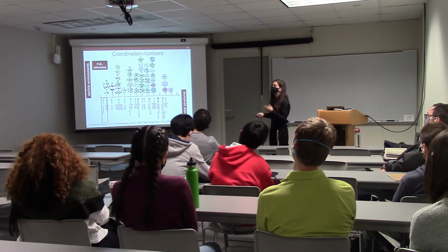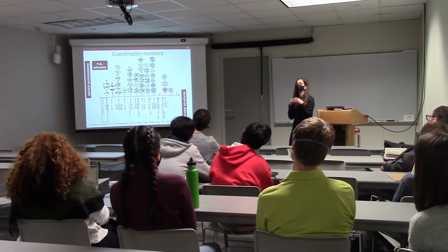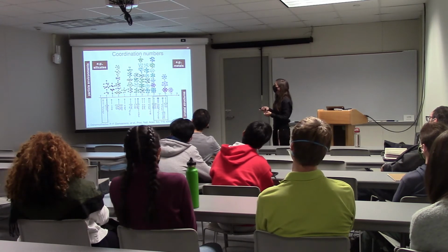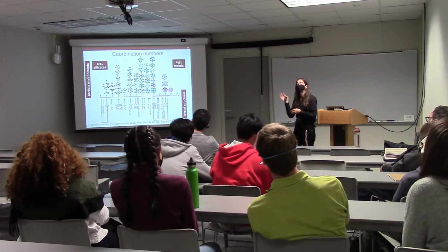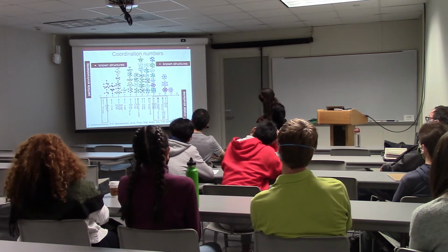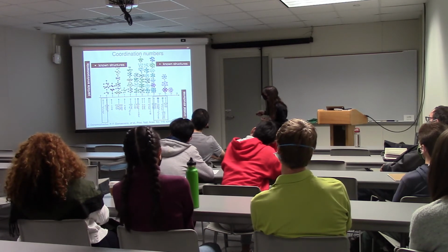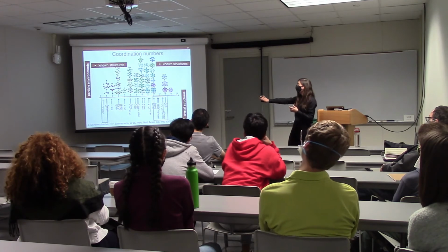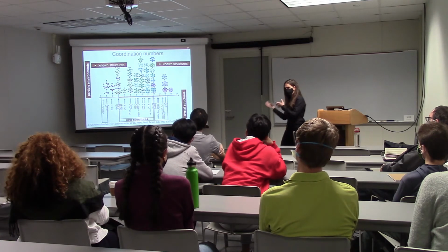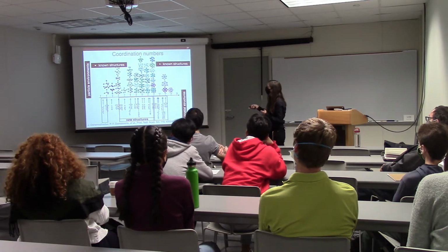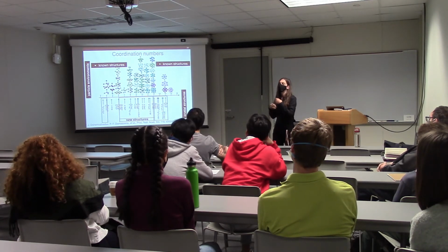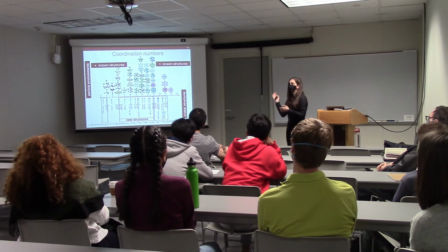So on the very left you have 4 nearest neighbors, for example, like you would see in silicates. Anything that's sp3 bonded would have a tetrahedral local environment. And on the right you see high coordination numbers, 12 or 14, like sphere packings, like you would see in metals. So that's where our known structures sit. I think the nuance that is probably lost here is that all the ones with the X's, the new structures, are printed in red, and they're almost all here in the middle. And if you still wear your chemist's hat, you'll find, okay, of course, these are one-component systems, and they have nearest neighbor numbers of 9 or 10 or 11, which no atom wants to have. That doesn't fulfill any octet rules, right?